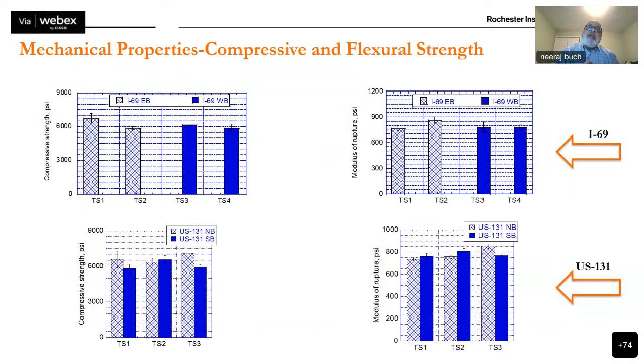So here's some data from the compressive strength. Hopefully you can see my cursor. This is comparing the long life with the regular concrete pavement, the regular concrete for I-69. And you can notice, if you recall, the target strength was 3,500 PSI or 25 megapascals. So compressive strength was really not an issue when it came to whether it was conventional concrete or long life concrete pavements. The compressive strength targets were met both for I-69 as well as US 131 concrete.